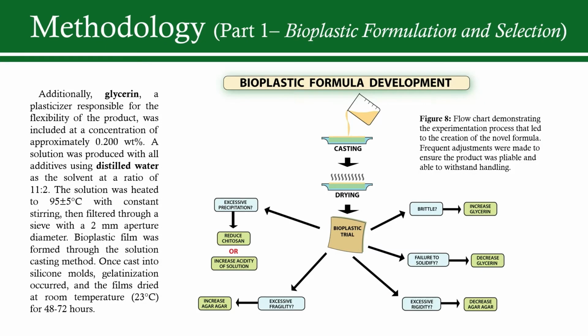After heating the mixture to approximately 95 degrees Celsius, the solution casting method was utilized by filtering the solution through a sieve with an aperture diameter of 2 millimeters and allowing it to solidify in silicone molds. 9 months of preliminary experimentation took place to synthesize the final bioplastic formula, with 60 various formulas tested before the final selection. This diagram shows the process I used to tweak the formulas once I had a basis.